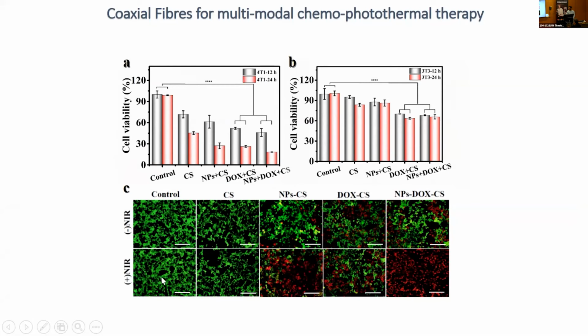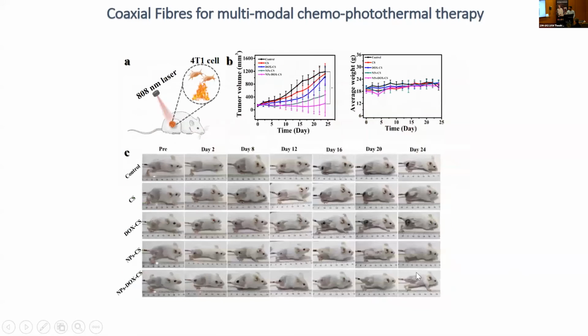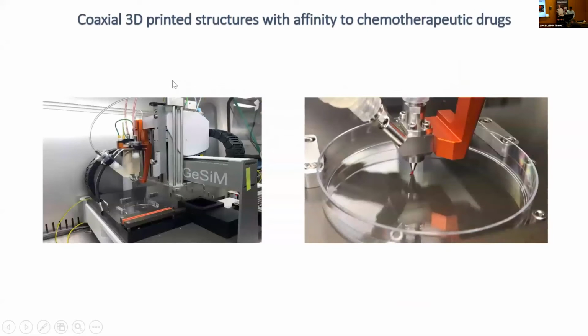We also did live/dead staining of the cells, which showed that the dual treatment with doxorubicin and the laser basically killed all these breast cancer cells. We also did in vivo studies, and similar results were observed, where dual therapy was capable of inhibiting the tumor growth.